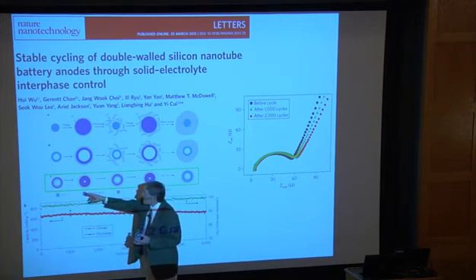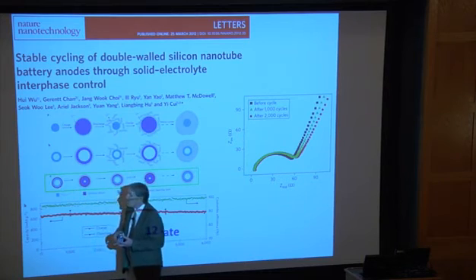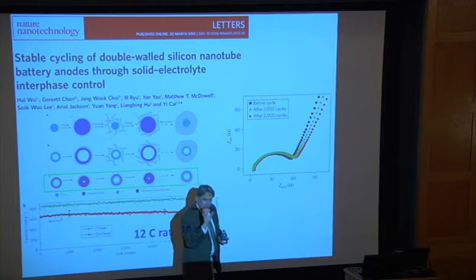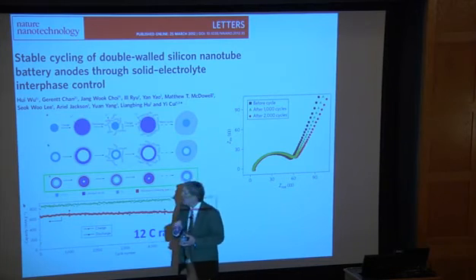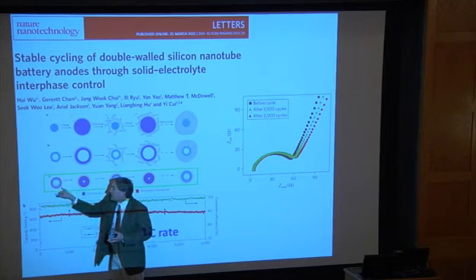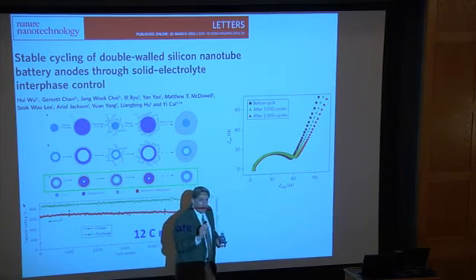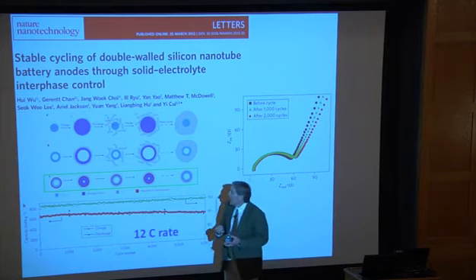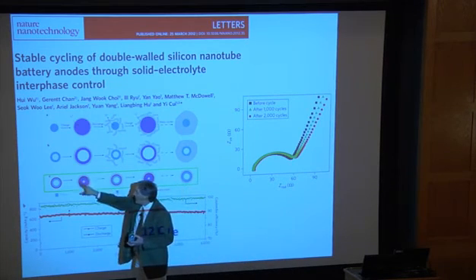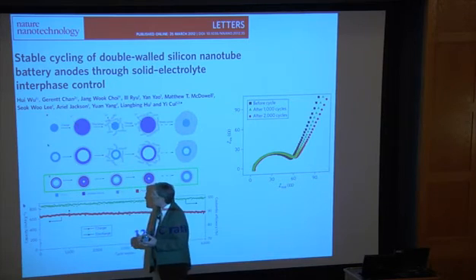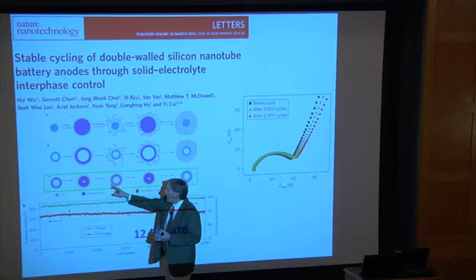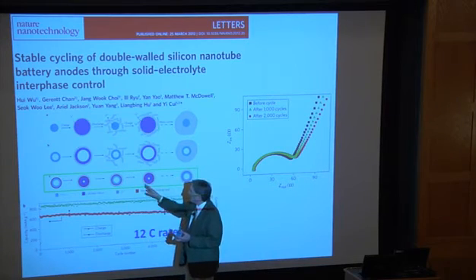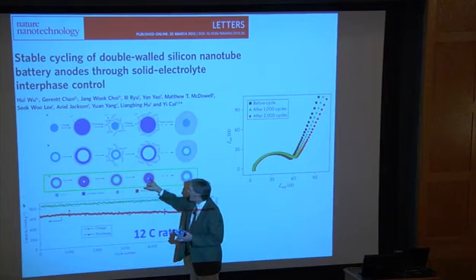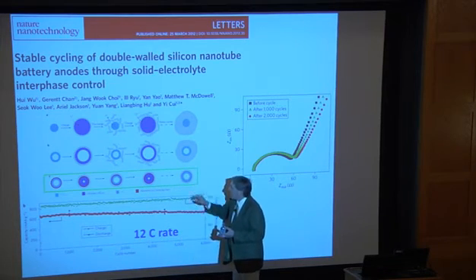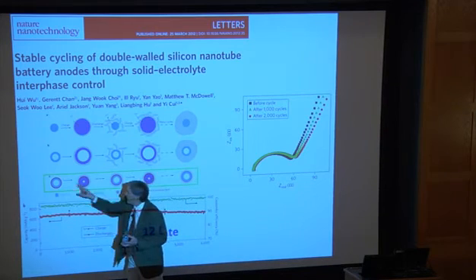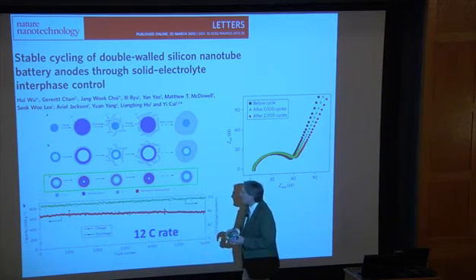And what they did then instead was to say, I'll have a hollow region in the core. That allows me mechanical expansion into the core, so some stress relief. And then over that silicon, I'm going to oxidize with a flash oxidation of silica, so SiOx of some form. And now that tends to help hold things together. It acts like an artificial solid-electrolyte interface. The growth of the actual solid-electrolyte interface, or lithium reaction products, solvent reaction products, is not excessive. So as you charge, you can see that it swells into the core center, and finally as you discharge, you get back a geometry that looks a lot like the original geometry, with some discharge reaction products on the outside.